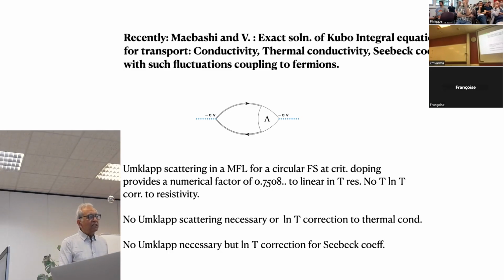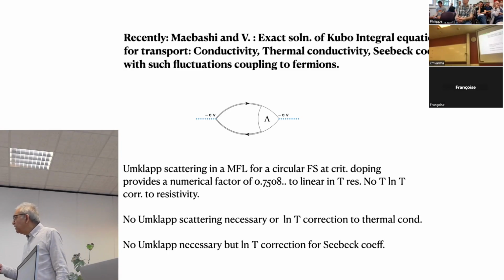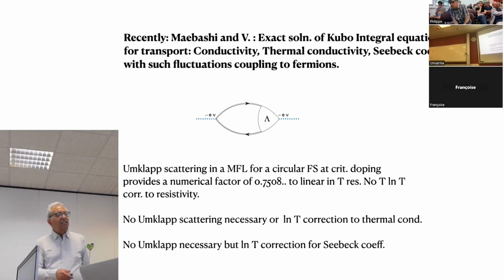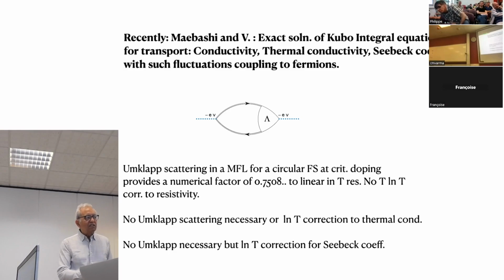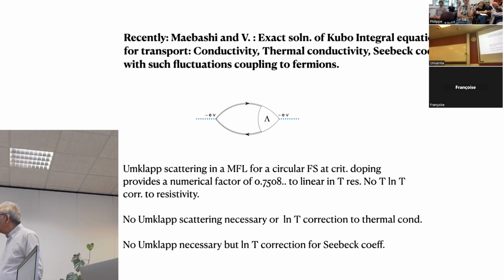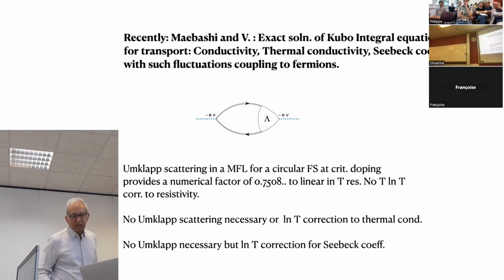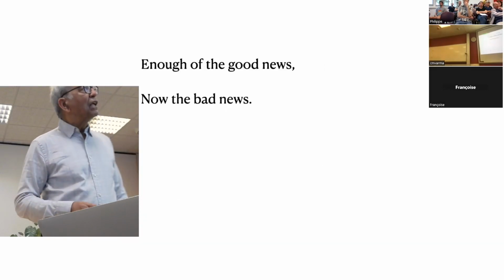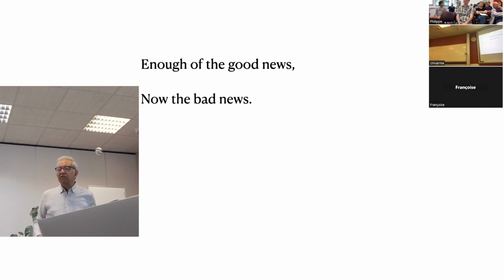And then you discover some additional things which you can derive, that there is no ln T correction to the resistivity. There's no T log T. Specific heat goes like T log T. That does not enter into the resistivity. No Umklapp scattering is necessary. Umklapp scattering will change magnitude, but see, without Umklapp scattering, the resistivity is zero always, but not thermal conductivity, energy transport, and even though thermal conductivity is carrying heat, the heat capacity log T correction does not enter the thermal conductivity, but it enters into the Seebeck coefficient. Okay, so that's that.